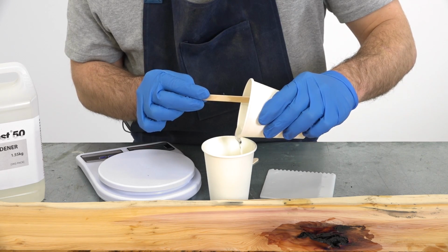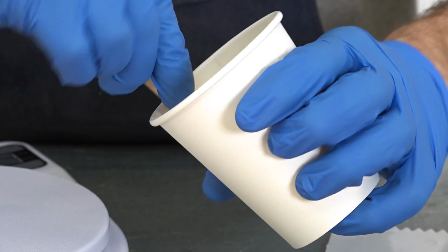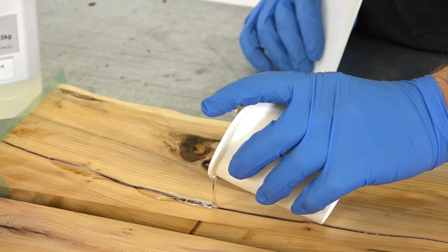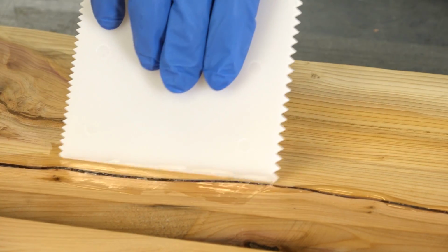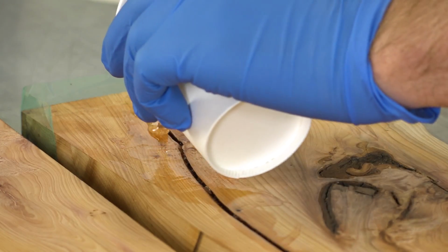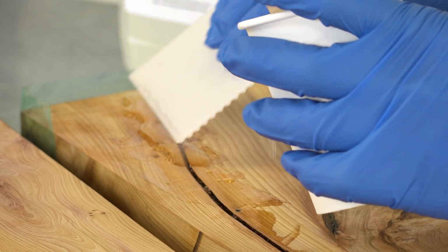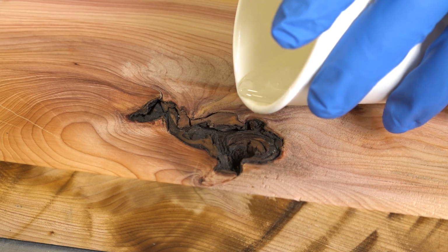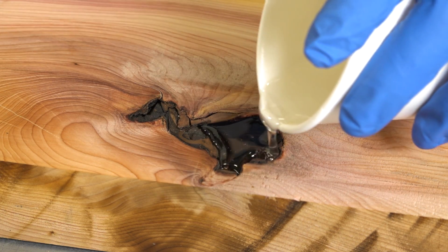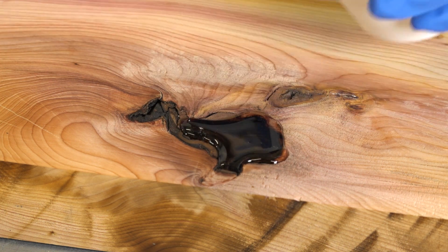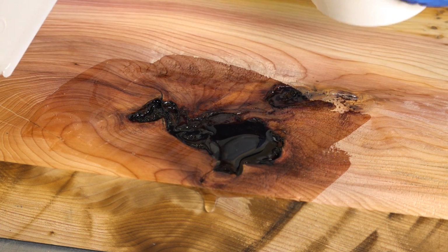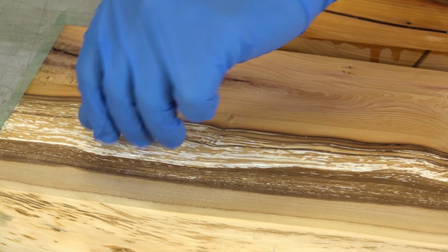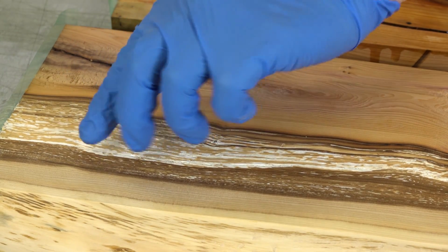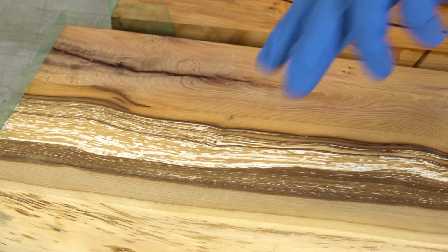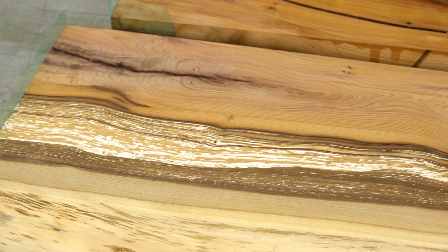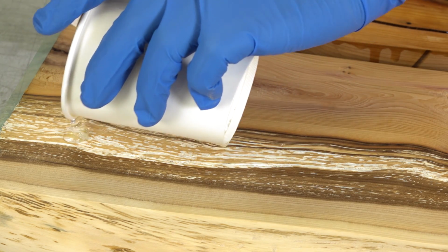Although this is only a small mix, when mixing epoxies it's best practice to double pot, mixing thoroughly once in one pot and then transferring to a second pot and mixing again, ensuring that no unmixed resin can find its way onto the job. As you'll see, some of these knot holes and features will actually take quite a bit of resin and need topping up more than once, but this is fine because at least we know the resin is doing its job and making areas like this knot hole or this flaky porous area much stronger.